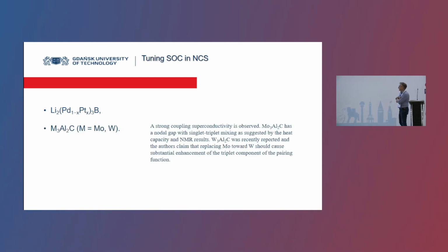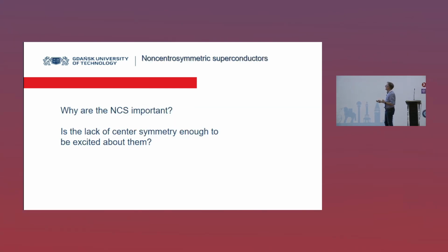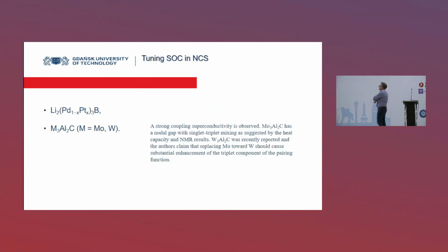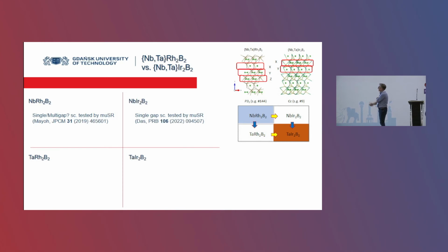Another system, a rather recent system, is molybdenum or tungsten aluminum 2 carbide. And again, tungsten is much heavier, so spin-orbit coupling should be stronger. Molybdenum is much lighter, and you expect that the effect will be much weaker. As far as I know, there are no studies published with the solid solution of the compounds. So we have 2 systems, and this is another one.